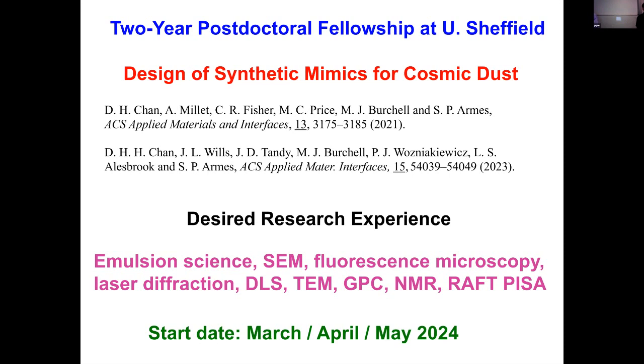We can cross-link, and we've done that by various chemistries. The one thing we can't do is add a bifunctional monomer during the synthesis of a second block. That doesn't work. What we do is add the dimethacrylate or diacrylate as a third block, and that just ties all those hydrophobic ends together. That works beautifully. For reasons I don't understand, statistical copolymerization doesn't work. We tend to get precipitate, etc. But the third block approach works really well.